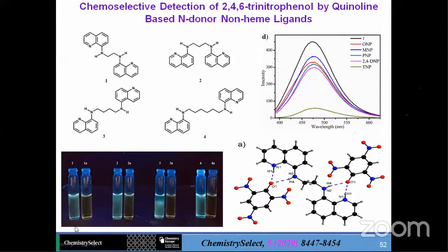You can see here, this is my starting ligand compound, and this is after adding trinitrophenol. These are fluorescent compounds, and this fluorescence is quenched after adding trinitrophenol, which indicates that these compounds can be easily quenched. These are the intensities you can see here. The first one is orthonitrophenol, then metanitrophenol, paranitrophenol, 2,4-dinitrophenol, and the last one is trinitrophenol. For the first four compounds the response is not so good, but TNP is reacting so nicely. Therefore we thought our ligands are much better for quenching TNP.